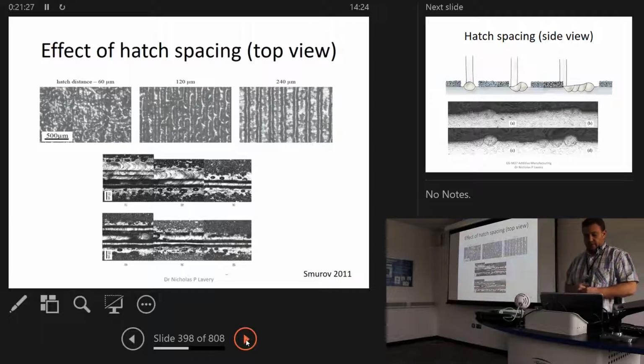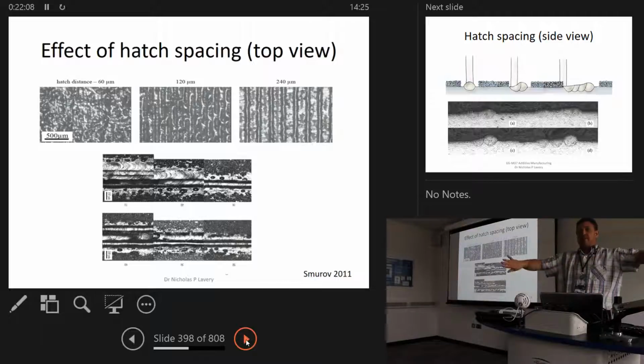One thing to point out is that we are dealing with powders with this, so that when we create a track, and these bottom two pictures show that quite clearly, there's a process by which when you're melting, you've got a build-up of pressure, very much like a power hose. If you're power hosing outside on the patio and you've got sand, when you point down your power hose to clean it, the sand will shoot up in front of it. There's a sort of recoil pressure. This is obviously on the molten metal. It's the same thing. There's an evaporation pressure or recoil pressure that's formed during the melting, which denudates or brushes the powder away from the melt.